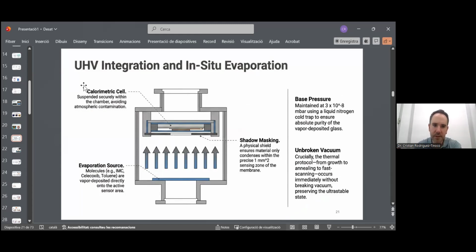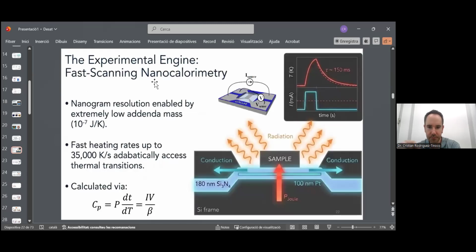On this substrate, where the material will deposit, we put our calorimetric cell. How is this calorimetric cell we use to characterize this transformation? This is this kind of device, which is a nanocalorimetry cell. This is a technique called fast scanning nanocalorimetry. It is just a very small device, like 1 centimeter square more or less.